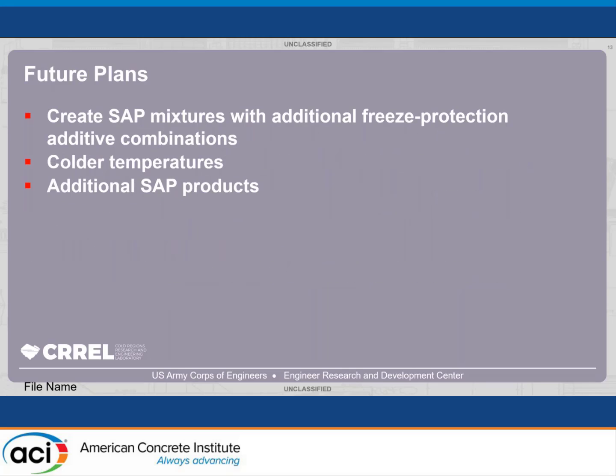Moving forward, some of the things that we could add to this small research study would be trying this with different combinations of those freeze protection additives. This was just one dosage of the freeze protection additives for the 6 mixtures. And we are from the cold regions lab, so we always want to go colder. This works at 23 degrees Fahrenheit. Does it work at 15? Does it work at 10? And in addition, we did just try one SAP product for this research.